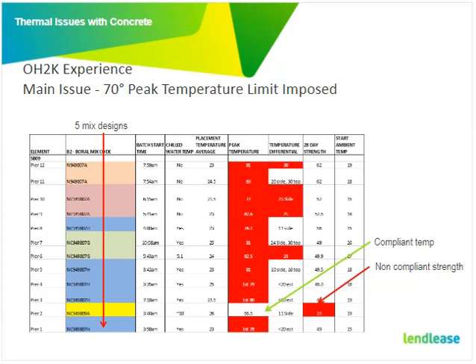You can see on the left here, these are the different mix types. Maybe I'll just explain. Early morning pours were done, chilled water was used, and placement temp was less than 26 degrees. This is mostly for the headstocks, just a standard headstock. That's the only compliant temperature that we had, 66.5 degrees. But we didn't achieve the 28-day minimum concrete strength. We were probably 5 MPa out, if I can read that correctly.